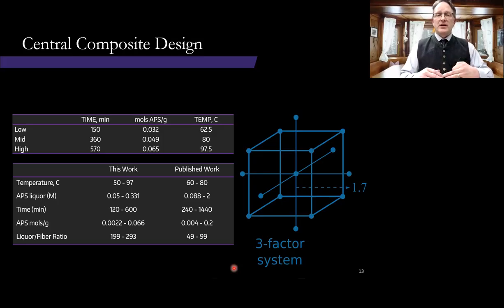As part of the process, we code and relativize the scales prior to analysis. And what the central composite design does is it allows for a quadratic response surface of treatment effects to be produced. Now, if you look at these published data, you'll see that they're fairly more aggressive and a little broader and higher in range. If you recall, I mentioned that the process for ammonium persulfate is not well documented in the literature. And the reason for that is, I guess the best way to describe it is most of the researchers are focused on the finish line. The fiber itself is a raw material for a finished product. And so they tended to focus more on creating CNCs, not so much on the process.